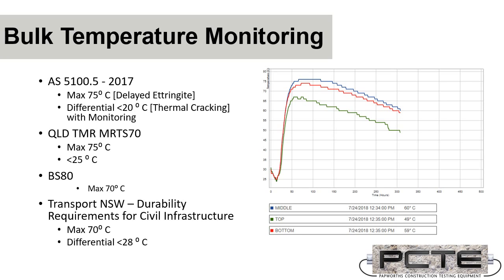Now, they do define monitoring, but it's not the monitoring that's going to prevent the strength issues, the cracking issues or the performance issues. It's the curing environment and the care taken during the pour that are going to control for these. Things like insulated formwork, delivery of cold water with concrete, and the use of the correct mixes for the application is what's going to meet these criteria.